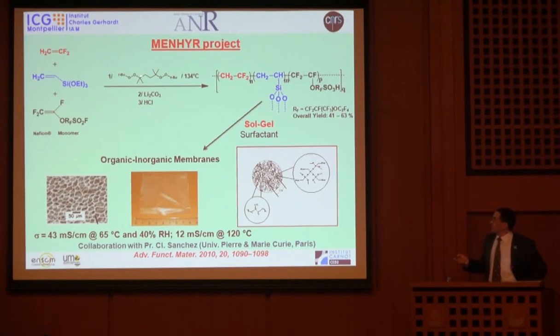After making the radical copolymerization, this was saponified first with lithium carbonate to have sulfonate, and then acidified with HCl to have sulfonic acid, which instantaneously, in a sol-gel process, thanks to Professor Clément Sanchez in Paris, we could achieve some membrane. You see, this is kind of a dense membrane, 50 micron, but more or less they are very dense, but very interesting because you blend some fluorinated polymers, made of PVDF